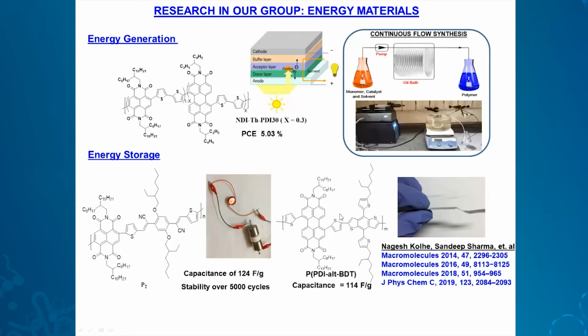So in our research group, we have evaluated these NDI type or PDI type polymers, DA donor-acceptor type polymers, as type 3 supercapacitor electrode material in combination with carbon nanotube. And their performance again was evaluated using N2200 as a reference material. And we have obtained good capacitance values and stability. This is a very important factor. Stability over 5,000 cycles with almost 100% retention of these values, and flexible devices also could be fabricated.